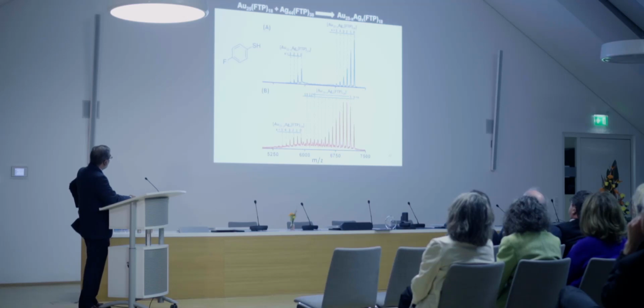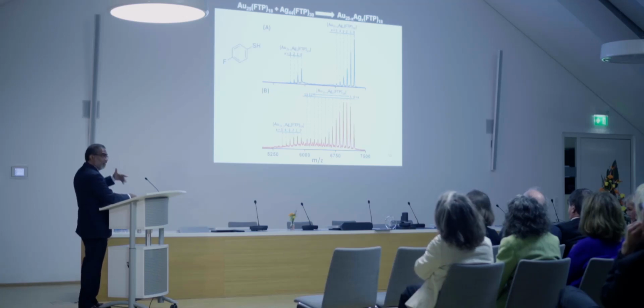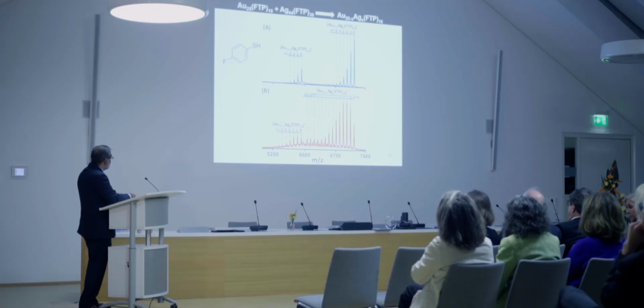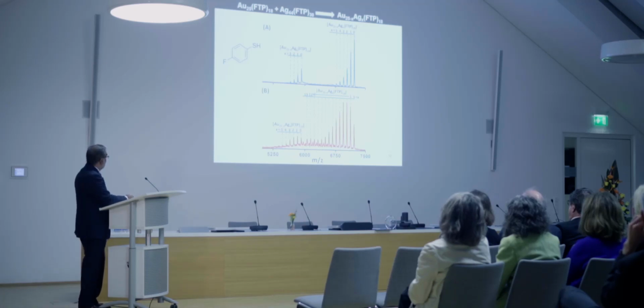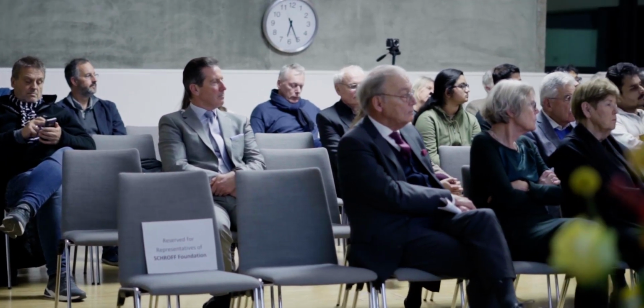So if I take a pure cluster of this kind, I'll get a peak like that, and this cluster will decompose or fragment in the gas phase to give you some peak like this. So these are the only two peaks that you would have if you take just this pure cluster. The moment you add this, of course, this will ionize and give you some peak which will be beyond this mass range. But then I started seeing something here. Suddenly peak 1 comes up, peak 2 comes up, etc. And here also some peaks come up. And these are nothing but exchanging one Au atom with an Ag atom, keeping the nuclearity the same, essentially a 25 atom cluster.